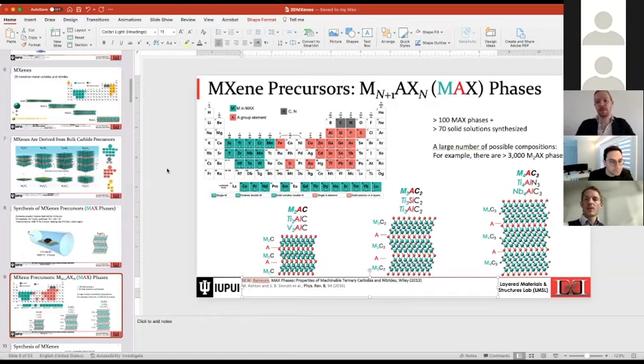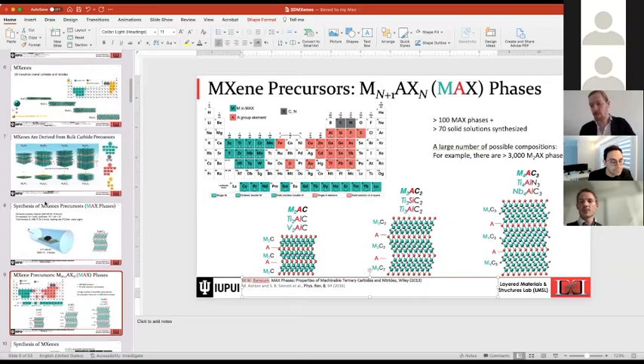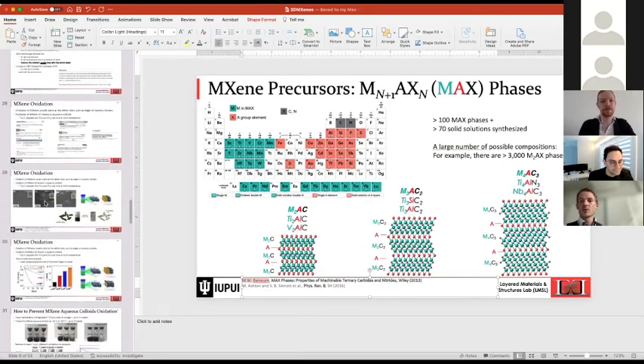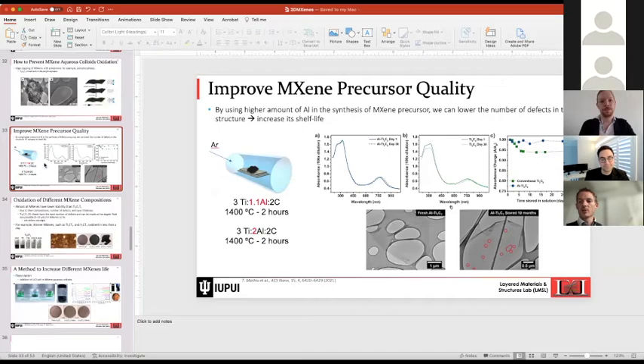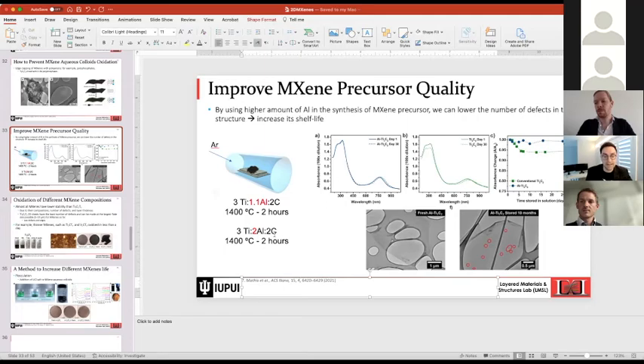Then you showed that the oxidation stability is quite significantly increased when you use a molar ratio of 2 of the aluminum. And the next question is how or why the stability of this MXene is then improved. So the exact mechanism, I would say, is a novel study that is not known, but the best way, based on the findings of this paper, and this is the only paper that reported the use of 2 aluminum,